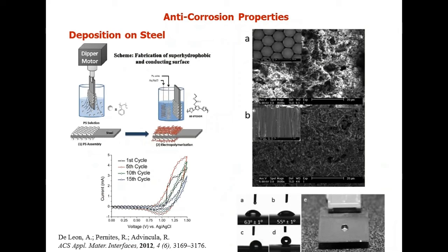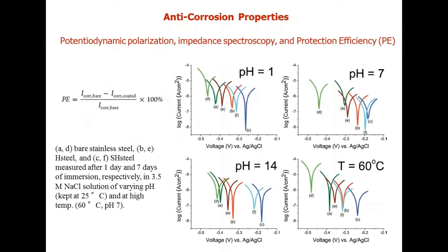Another is that we investigated their anti-corrosion properties. In this case, the anti-corrosion was tested by looking at the wetting behavior, the electrochemical properties based on polarization and electrochemical impedance spectroscopy, just to confirm that we are looking at the same film. This is the SEM as well as the contact angle superhydrophobic behavior. And here are the polarization plots that change with different pH. The bottom line is these films are stable even at a high and low pH. On the other hand, using the film at 60 degrees C shows that they have very good stability. Essentially, the film that we are after is this blue colored polarization behavior.